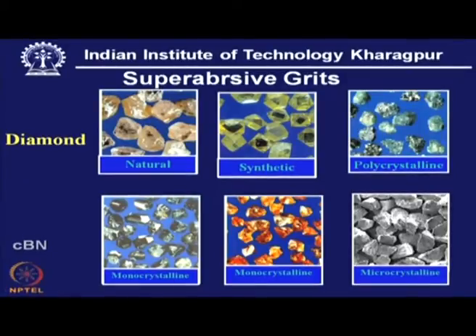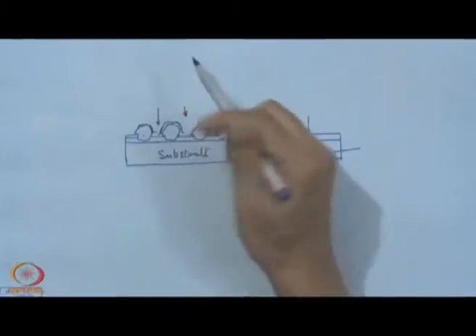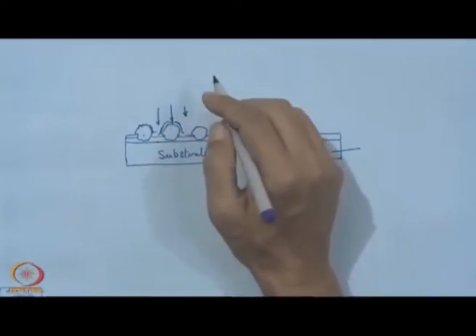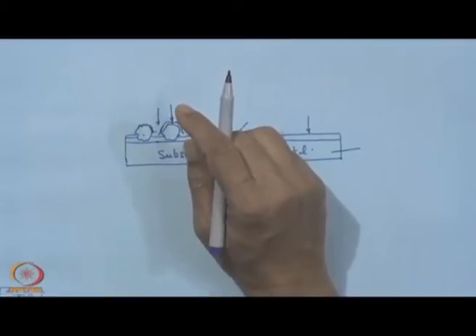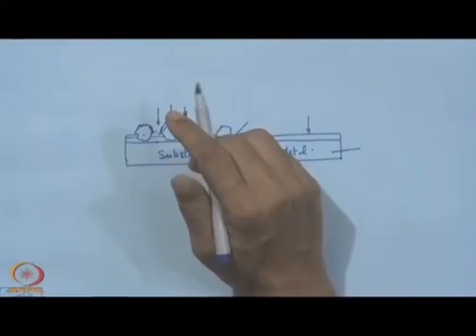So, in this case we must adopt a certain process, method or technology to roughen this surface. It can be thermal etching in the presence of oxygen, or it can be some chemical etching, only to create some pitting, micro pits, micro voids over this surface. So, it can have better anchorage. So, we find that though synthetic crystal has many advantages, its selection cannot be obvious, and utmost care has to be taken so that it can be well anchored in the bond, and at the same time there is no material deposit on the crystal surface because of some inherent conductivity, which is due to the presence of the catalytic agents used during the synthesis of diamond.